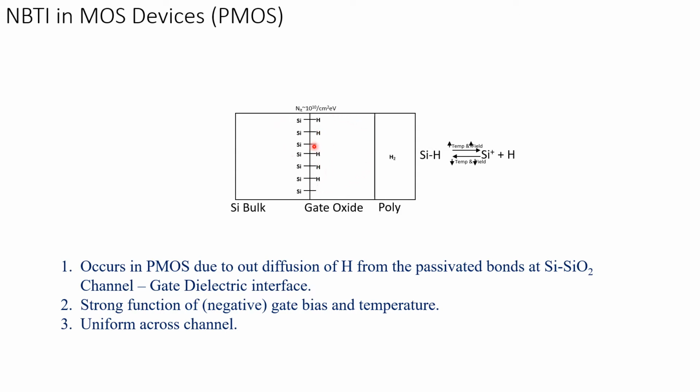Well, since this phenomenon is happening discretely, that is, one bond breaks, another bond breaks, then this out diffusion happens, you can model it using the forward and reverse reaction rates, or the kinetic theory of reaction rates. You can model this and then convert it into electrical equivalent modeling. So that is how it is actually done. However, my question is, what kind of distribution will this be? Will it be Gaussian?